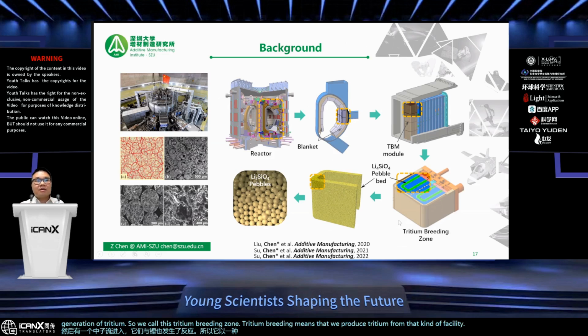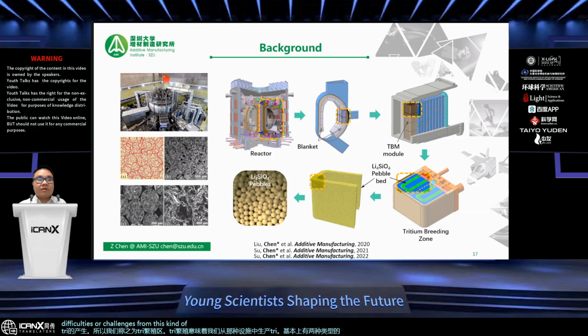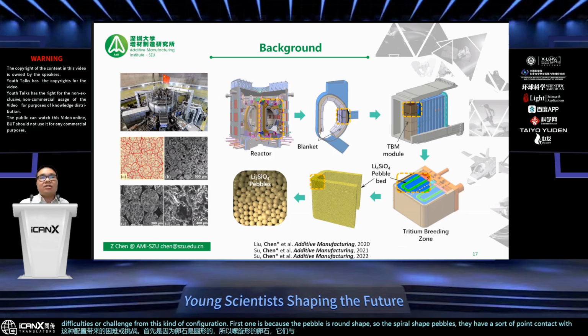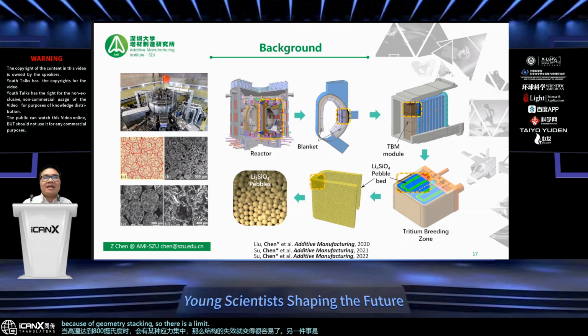There are basically two types of difficulties or challenges from this kind of configuration. First, because the pebbles are spherical, they have point contact. At high temperature, up to 800 degrees C, there will be stress concentration, and then failure of the structure becomes very easy. Another thing is because of geometry, stacking has a limit of about 70% stacking ratio, so we cannot go even higher. Then there's a problem with increasing tritium breeding efficiency. So these are the two main drawbacks, and people are working hard on this issue.